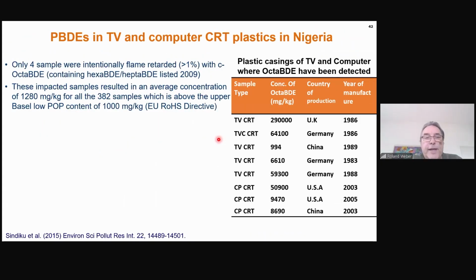And when we then analyzed the PBDE, we found that from the 380 samples, only 4 samples were intentionally flame retarded with commercial octa-BDE. But these 4 samples were already sufficient, when you would mix the whole plastic, that this plastic is above 1000 milligram per kilogram and therefore above the low POP content. 4 samples out of 400 samples.